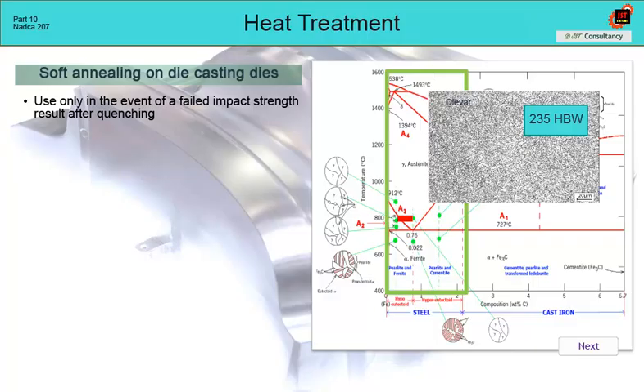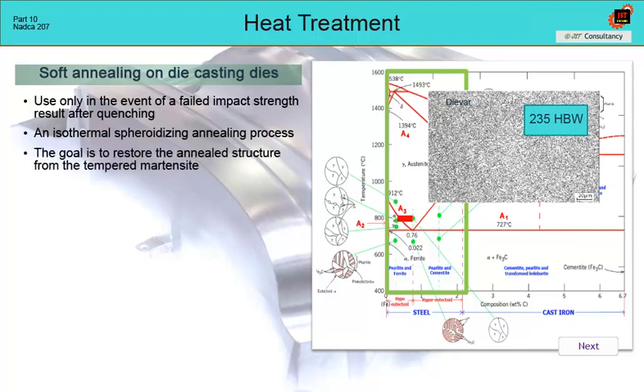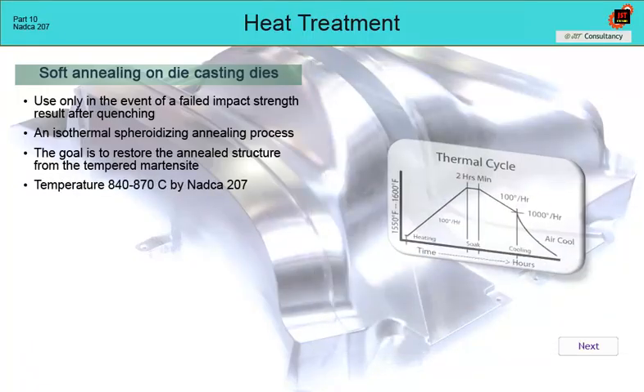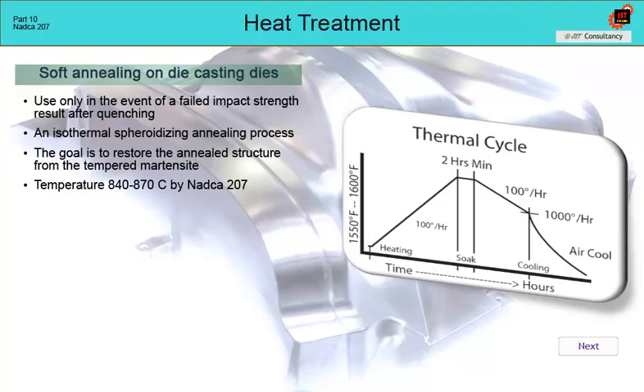It is an isothermal spheroidizing annealing process, the purpose of which is to restore the original pearlitic structure by the transformation of tempered martensite after unsuccessful quenching and tempering. The usual annealing temperature for materials according to NADCA 207 is 840 to 870 Celsius.